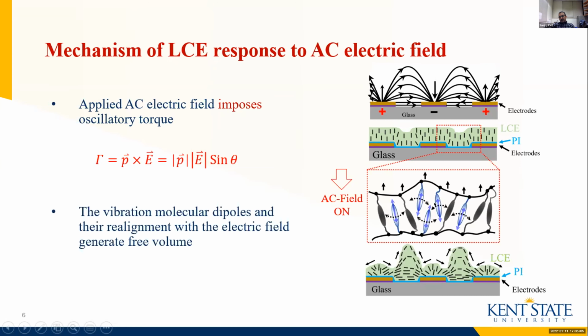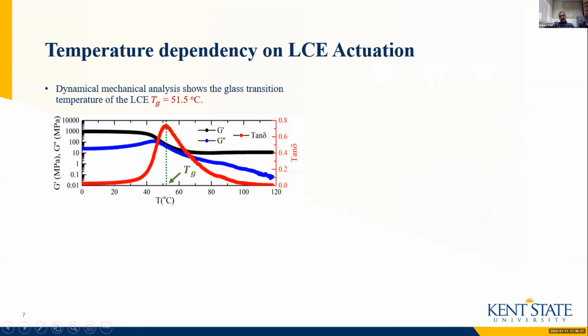Also, dipoles want to realign with the applied electric field. So the vibration of molecular dipoles and their realignment with the electric field generate free volume in the system. As a result, following this electric field distribution, the liquid crystal elastomer expands in the inter-electrode region. The dynamical mechanical analysis shows that the glass transition temperature of our elastomer is 51.5 degrees Celsius.